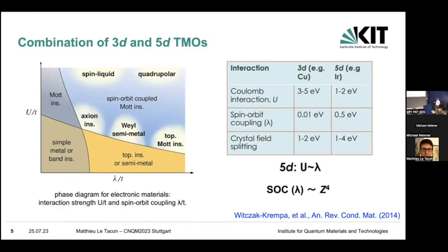And on this horizontal axis is the spin-orbit coupling, which also drives metals into funny states, semi-metallic states or topological insulating states. And if you mix the correlations with the spin-orbit coupling, there's a whole new world that opens. The idea here is that the spin-orbit coupling grows with the number of electrons in the system. So 5D metals like iridium or osmium are great because they have a sizable Coulomb interaction and a spin-orbit coupling which is strongly increased compared to the 3D metals and becomes sizable in comparison with the Coulomb interaction. So that's really where this new physics appears.